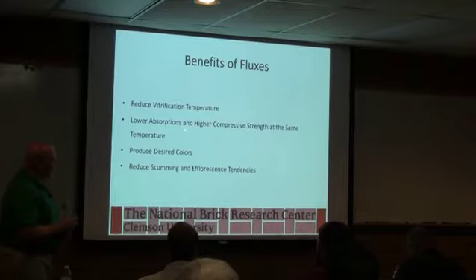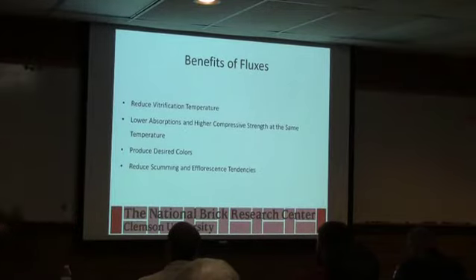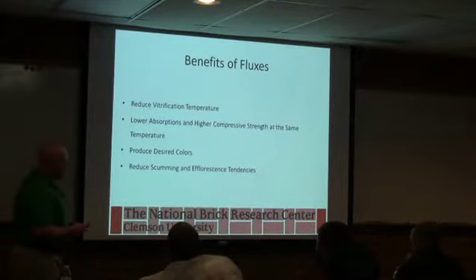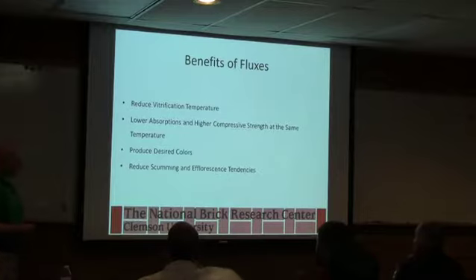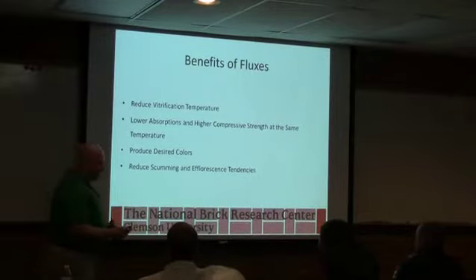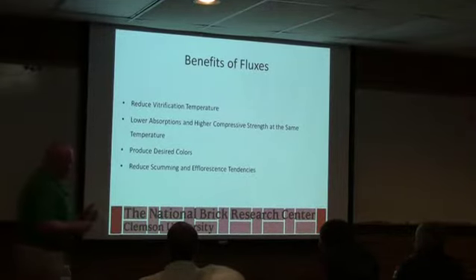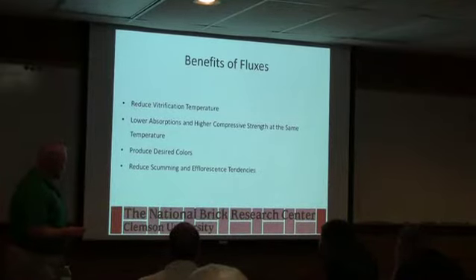And we've gone from water absorptions above 15 percent at the same temperature with just a little bit of some sodium additions down to below 8. It's still, for that climate, I'd like to see it even lower, but you can do those kinds of things. Sometimes you can get some odd colors out of these additives. They will intensify sometimes the iron or the manganese. Typically, as the water absorption goes down, everything becomes darker, and you can get more benefit out of that.